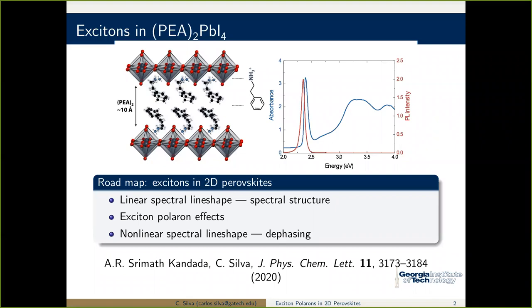We form structures that look a lot like multiple quantum wells. We have a rather thin quantum well separated by this barrier of essentially vacuum with these organic cations in between. And so this gives rise to very strong excitonic properties. So on the right, we're showing the absorption spectrum of this material. This is reminiscent of what a two-dimensional semiconductor might give you. And we can identify somewhere some bandgap, and down from the bandgap, we have a very well-defined resonance that is basically an exciton.